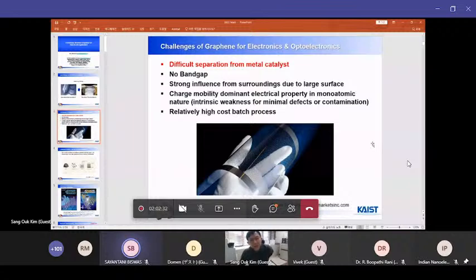But nowadays, the more critical issue is the preparation of high quality large area graphene itself. It's well known that on the surface of copper or nickel metal substrate, you can apply the CVD method to make a high quality graphene. This protocol is really well established, so you can be quite reproducible. But after this synthesis step, you need to separate the single layer graphene from the bottom substrate. But the adhesion between graphene and the bottom metal substrate is rather strong. So high throughput substrate transfer is quite challenging.